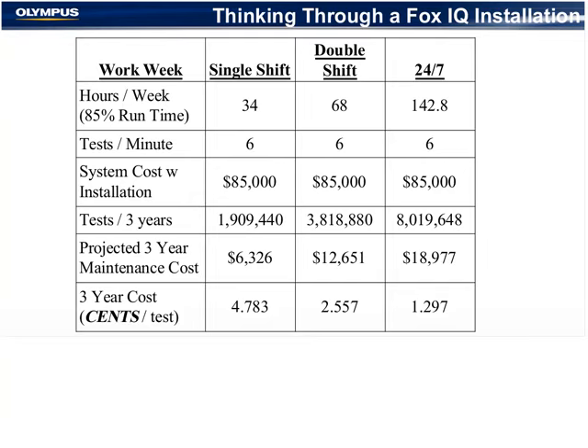I show the system cost with installation. There's an additional fee for traveling out and spending a couple of days to commission the system that's included in a ballpark way in that number. Then I show the number of tests for 3 years based on the volume. And in the end, the maintenance cost is in there, which is really about the X-ray tube needing to be replaced about every 3 years for a single shift operation. So when you put all of this together, with these assumptions, the cost per test is between 1 and 5 cents.